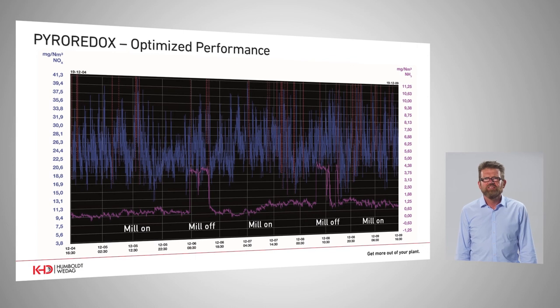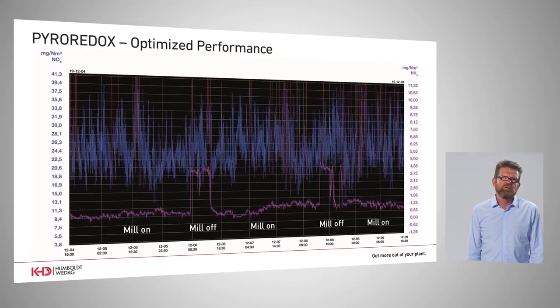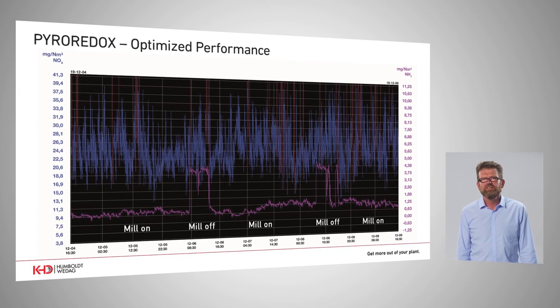A screenshot shows trends of NOx emissions and ammonia slippage over a period of five days. The NOx emission scale goes up to 40 mg; in average we were always below 30 mg. The ammonia emission was normally, with the raw mill switched on, on a level of 1 mg per normal cubic meter. Only if the raw mill was switched off did the external circuit of ammonia unload and emission go up to 5 mg — which is also very low in comparison to other plants operated with SNCR systems.